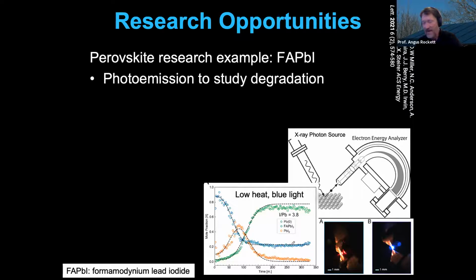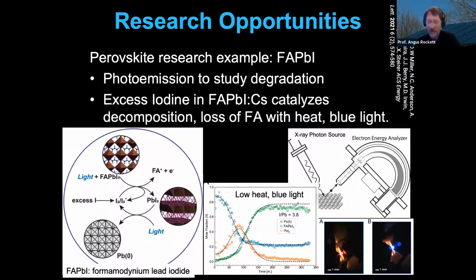The blue is the ideal material that we'd like to have, and you can see that decreases as we start to expose the material under low heat to blue light. Initially, we see an increase in the lead iodide signal, and then that eventually changes and we get metallic lead that forms. So that's a problem. So what we've concluded is that there's a catalytic decomposition of the FAPI material, losing formamidinium initially, and then going on to lose the iodine to form lead metal.